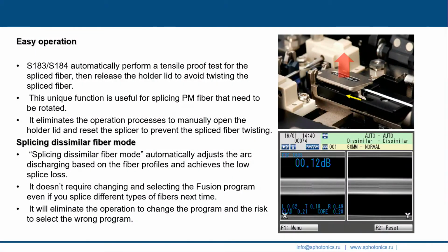So actually these splicing machines can automatically perform a tensile proof test for the spliced fiber, then release the holder lid to avoid twisting. It is really cool. It is really nice because if your fiber is a little bit rotated and there is some mechanical stresses inside, it can really damage your splice. It can make the splice with bigger losses and with worse extinction ratio.